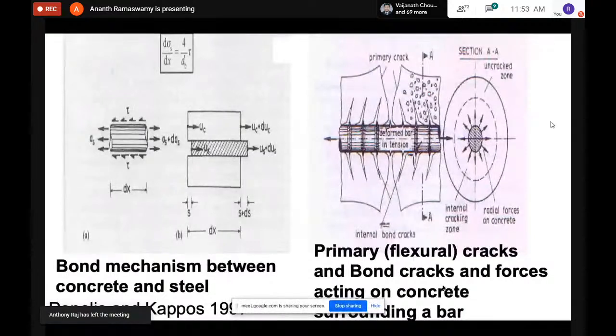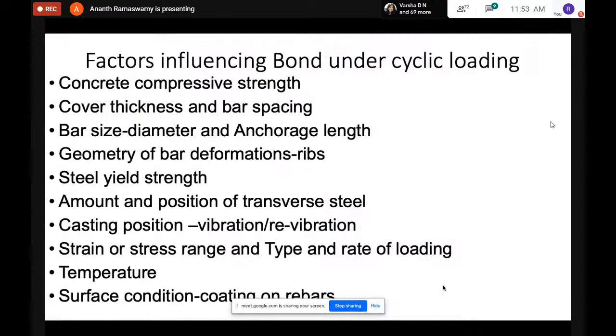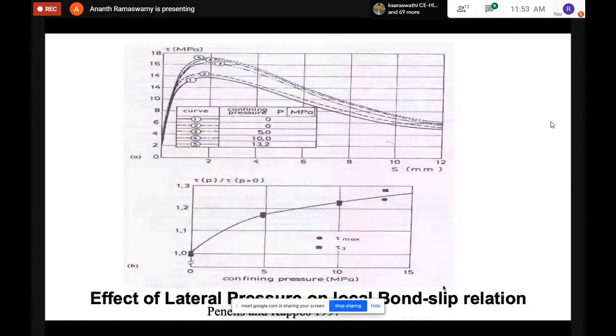This is an illustration of a bond slip and how bond behavior is an important parameter in your design and repair. So factors influencing bond under cyclic load: concrete compressive strength, cover, bar dia, geometry of bar, yield value, position of transverse steel, casting position, vibration, revibration, strain or stress range, temperature, surface condition, etc. Effect of lateral pressure, of course, confining means higher strength and improved bond. Bond also improves, as you can see in the plot below.